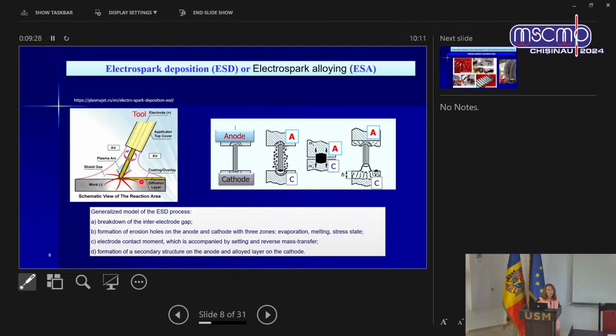In the air, you have very good things. If you make it in the air, you have a lot of nitrogen, so in this case nitrogen can also enter the coating. And like this, you can receive titanium nitride, which is very good.